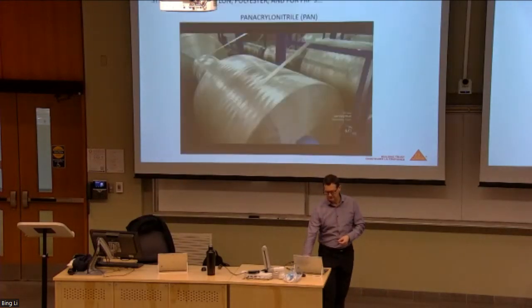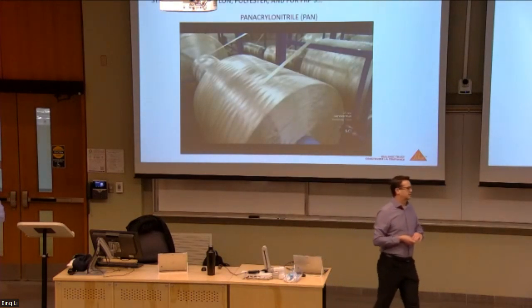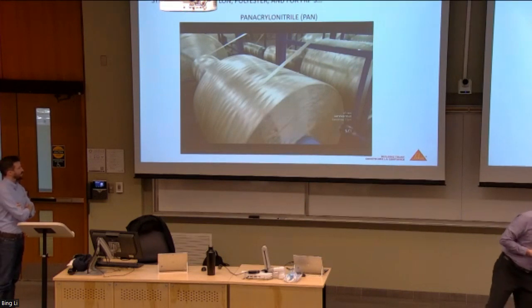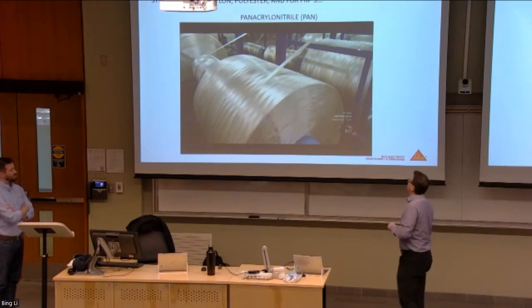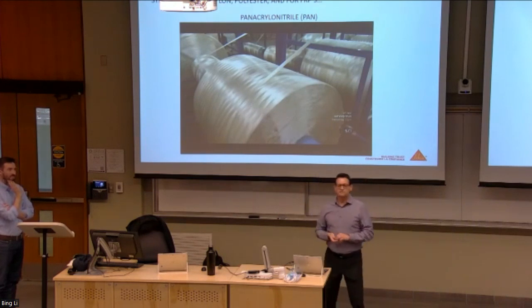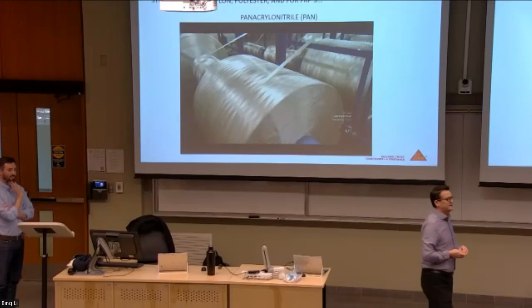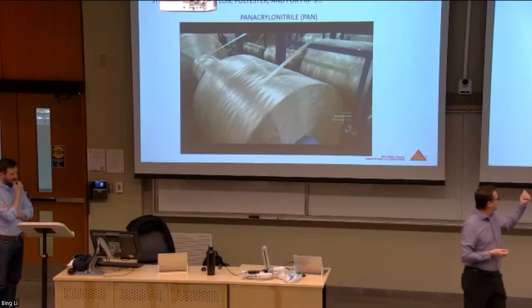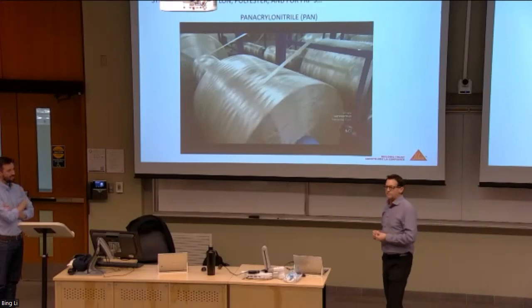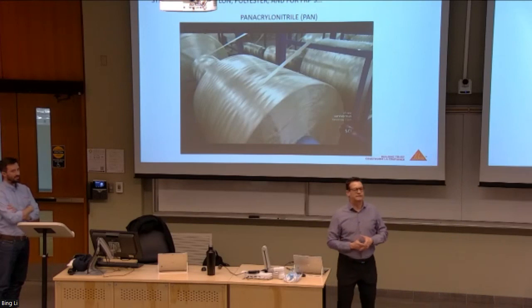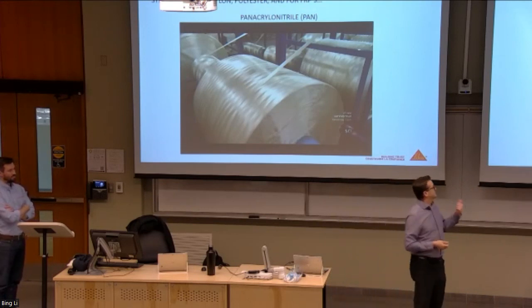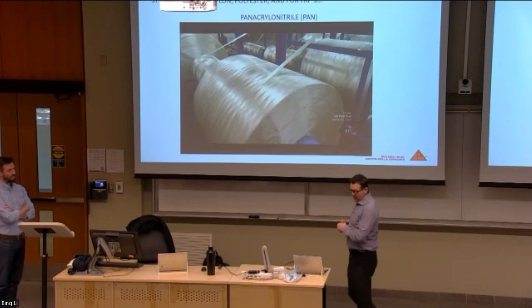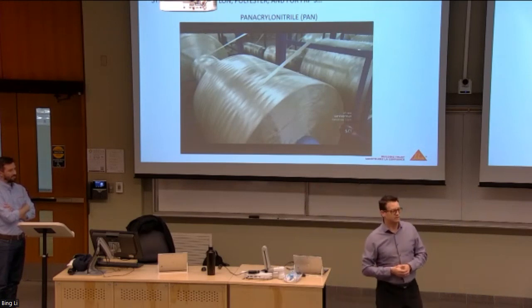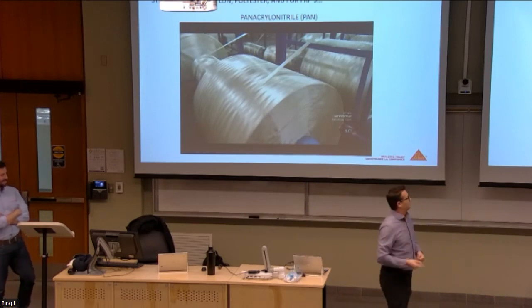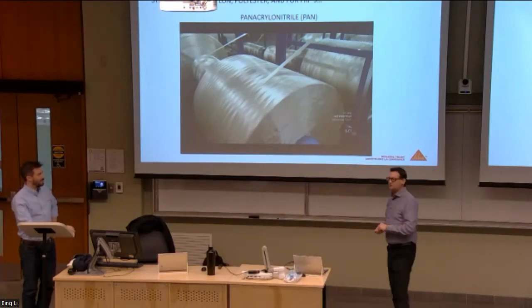Sorry, I went backwards. So this product starts out its life as a strand. Much like a nylon or a polyester, these strands are synthetic in nature, and they go through a roving process like this. But for carbon fiber, and the properties that these products exhibit in the field to give you added flexural strength, they use a strand called polyacrylonitrile. I think I've only said that once correctly in my life, and today wasn't the second time. So we call it PAN for short. These are called PAN strands in the field.